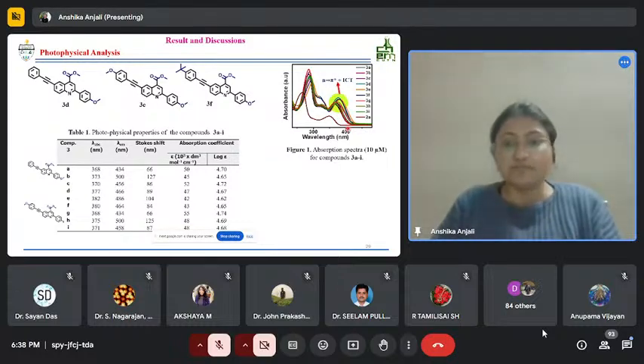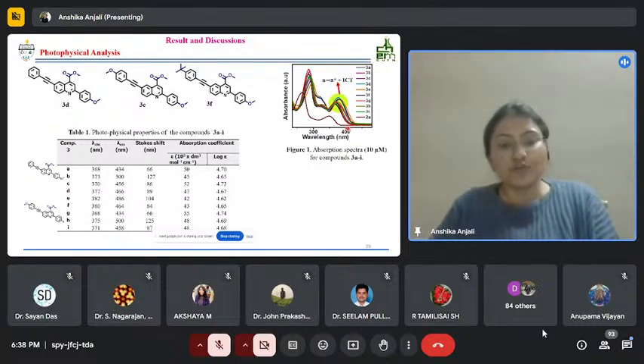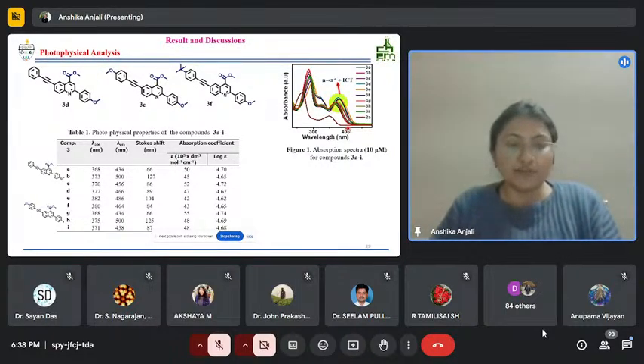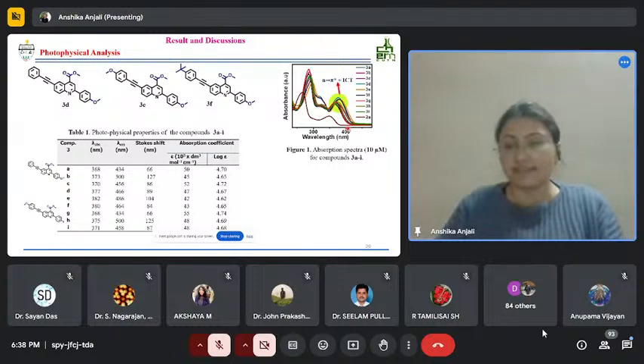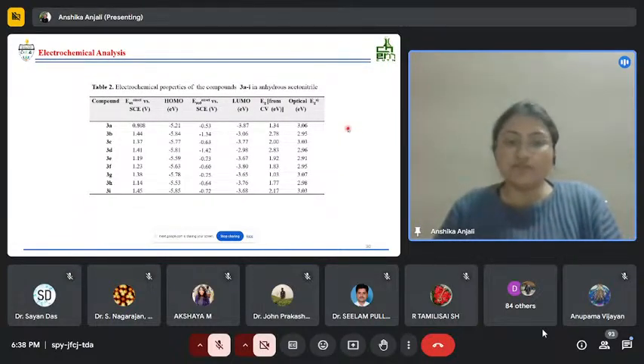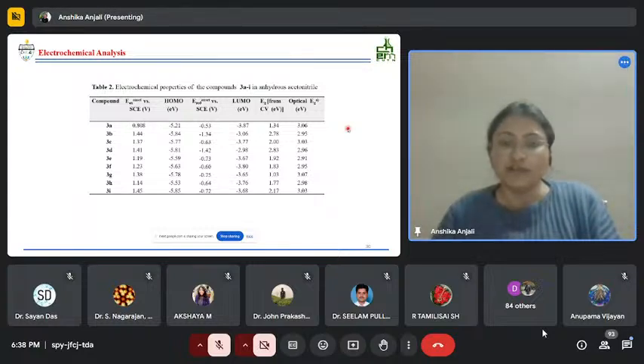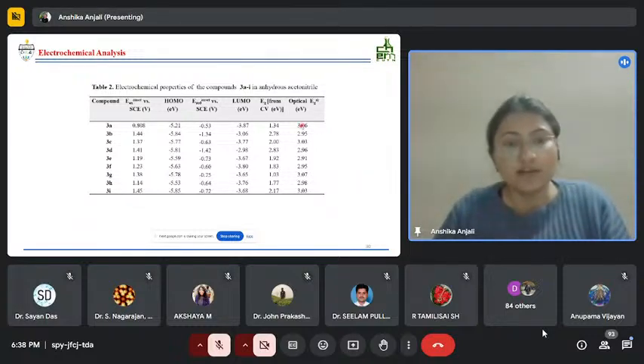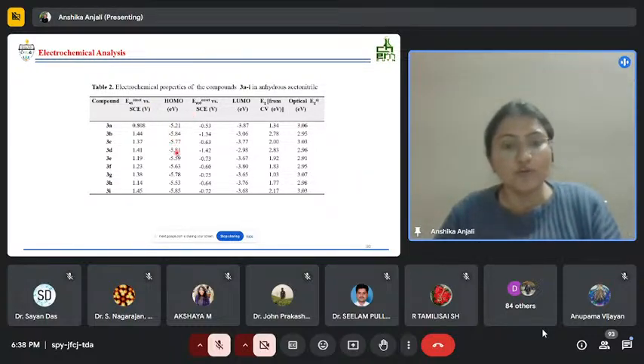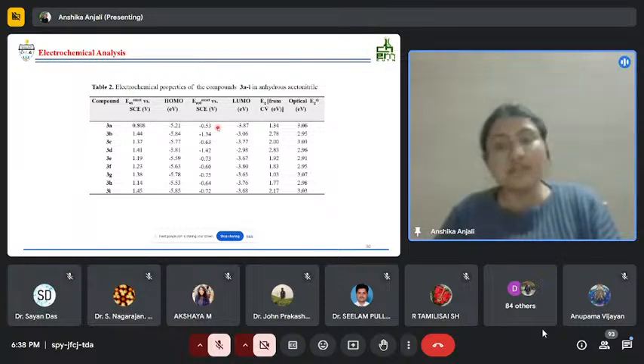From the emission spectra we have recorded, we have calculated their Stokes shift values as well, and the highest Stokes shift values here were observed for compounds 3B and 3H. The reason for higher Stokes shift might be because of the reorganization of this molecule in the excited state. For these compounds, we have observed peaks in the negative as well as positive potential in cyclic voltammograms. From the onset oxidation potential, we have calculated the HOMO energy levels, and from their onset reduction values, we have calculated their LUMO energy levels. The calculated band gap values were in accordance with the optical band gap that we have calculated from absorption onset values.